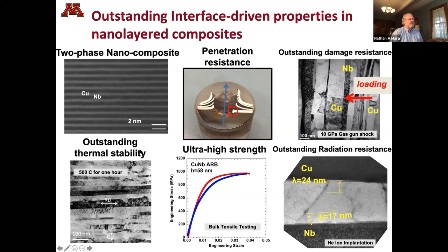They can have outstanding thermal stability. Here's one that's made out of copper and niobium. You can anneal this for 500 degrees C for an hour, and nothing happens to the structure. That's half the melting point of copper, which is one of your constituents. You can deform these. We'll talk about this at length here. In this case, 58 nanometer layer thickness, and you can load these materials up, and they have a flow stress of about a gigapascal. That's similar to what you'd see in a lot of steels. Although, in this case, we're not alloying anything. We're not playing any tricks with chemistry. We're just playing tricks with interfaces.